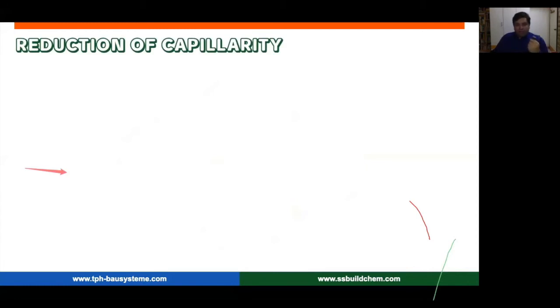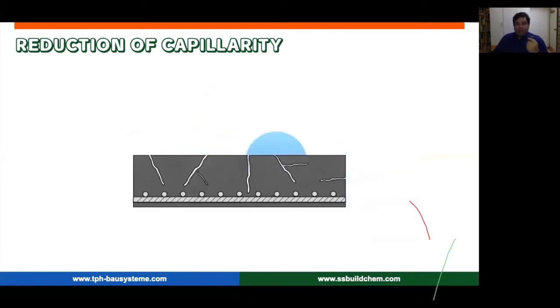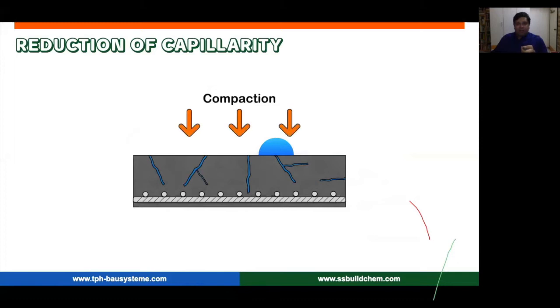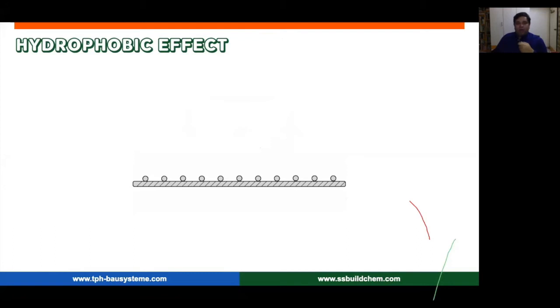So, the first principle, if we take it, is reduction of capillarity. You can just consider that this is your concrete, and concrete will tend to have all these capillaries in it. If you're using the right kind of integral waterproofing additive, then in the absence of it, the water can travel very freely through the capillaries. But with the right additive, your compaction is improved. And when your compaction is improved and your water is reduced, automatically the amount of your capillaries goes on reducing drastically. So in this case, very little water is able to go through your particular capillaries.